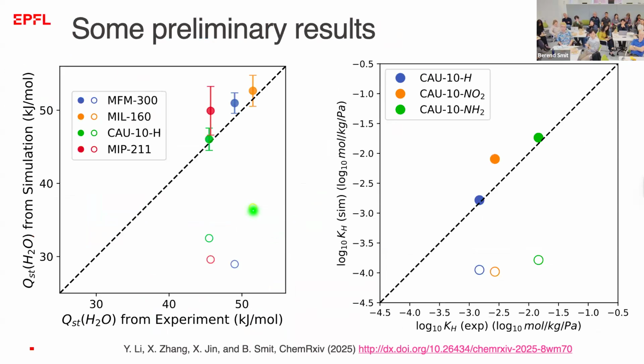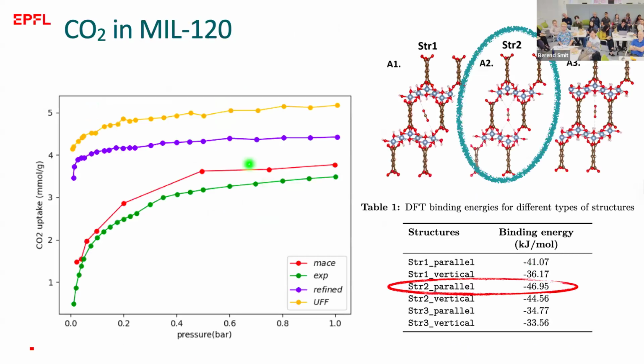It's really impressive, the improvement you can get. These were the experimental data with the classical force field. This is now with this fine-tuned model. We really get the heat of adsorption and the Henry coefficients correct. And also this one, the annoying one. So this is now the adsorption isotherm, and it agrees really well with the experimental adsorption isotherm. And what was actually going on? That's also the reason why water was so difficult.